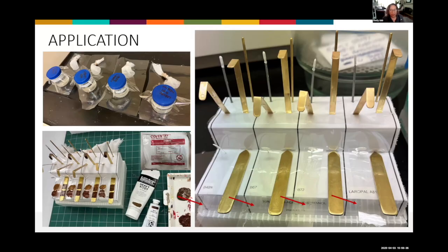I had also set the used tea bags in the fume hood to see how long they would take to dry. It was really fast. After an hour, none were sticky except for the Laropal A81. After 4 hours, I couldn't smell anything on any of them. After a 1-day check, all the bags were fully dry with no scent at all.